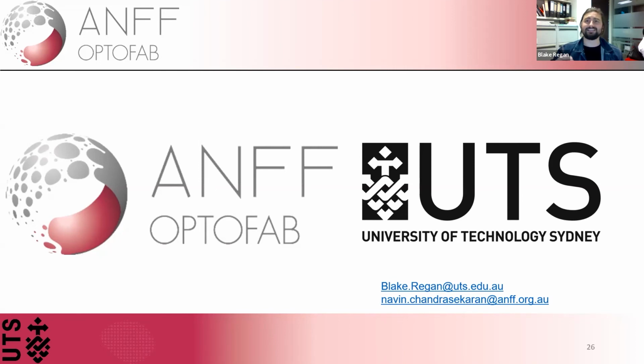I moved over to Caesar resist with a tungsten metal mask, which I then use contrasting chemistries of SF6 to etch the tungsten and oxygen to etch the diamond, which generated a tungsten oxide layer on top of the tungsten, which is basically impervious to any oxygen-based etching. So that's a really neat way as well of counteracting the charging problem, because it already has a metal layer that's already necessary for the fabrication process.